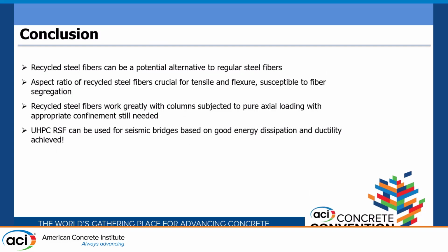So what are the conclusions for this project? We saw that recycled fiber has good potential as an alternative to manufactured fiber. Aspect ratio is very important for tensile and flexure. Again, it's going to be very susceptible to fiber segregation if you use a higher aspect ratio. Recycled steel fibers will work in pure axial columns. And lastly, for seismic bridges, it's pretty promising. It has good energy dissipation and high ductility achieved.